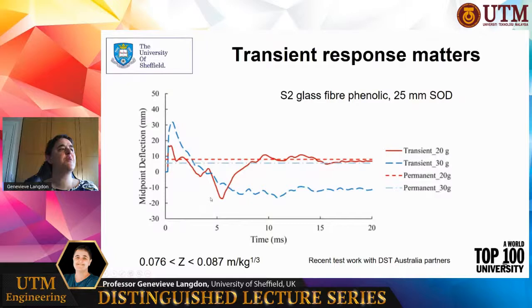And then you see that the panel goes back to a reasonable post-test permanent deflection of around about 8 millimeters. So if you were just looking at this panel afterwards, you would have no idea that it had done this very interesting transient response, because it just looks like it's deformed a few millimeters and that was it.